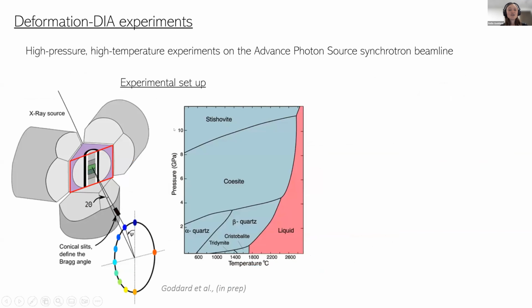To begin with, I'll show you some experiments looking at whether we can identify that quartz-coesite weakening in these natural samples. We do them in a high pressure, high temperature multi-anvil press, which you can see as a schematic here. It's known as the deformation DIA. These use really small samples, about 1 millimeter across, in order to get to really high pressures, as I said, of about 70 kilometers deep in the Earth. So we can take these rocks up into the coesite field by raising the pressure, and then we can subsequently bring them back down. So we're going through both the quartz to coesite and the coesite to quartz transition.